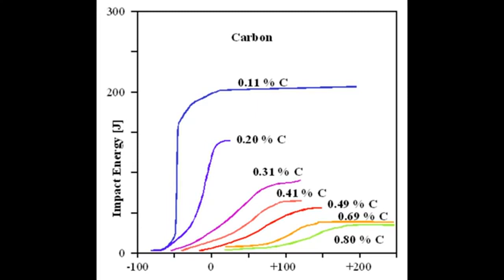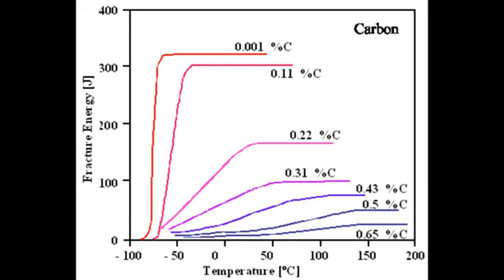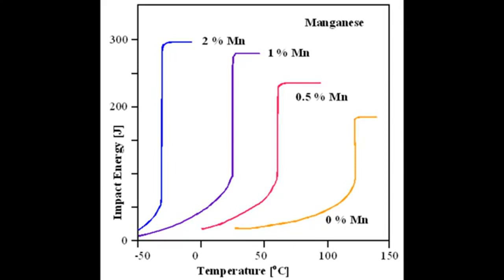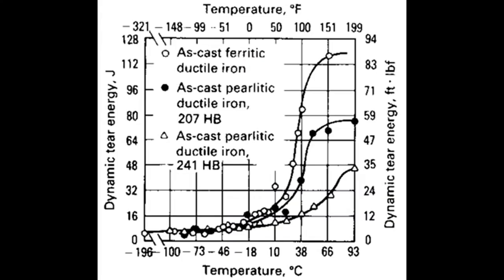Because, of course, the iron that was being forged was not pure elemental iron. We leave that to dwarves who dig too greedily and too deep. The presence of carbon, manganese, chromium, molybdenum, all sorts of other random little bits and pieces would all have their own effect, and more on some of those later. But it just so happened that the mix of trace elements in iron produced at the time placed the transition point squarely in the operational range of temperatures that warships would experience, with most of that transition occurring somewhat at the higher end of things.